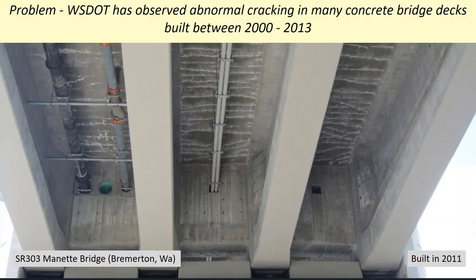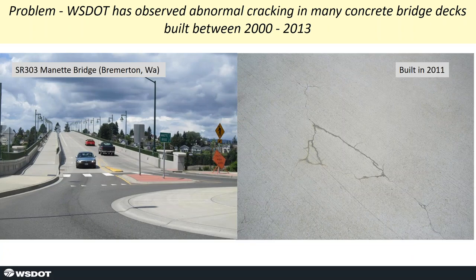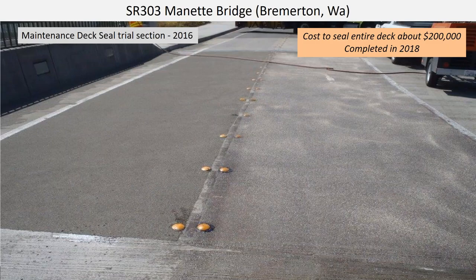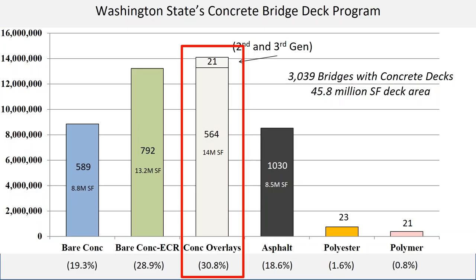And then on the bottom side, you can see for whatever reason, whatever combination of reasons, the deck had a lot of cracks in it from the very beginning. And we were recognizing this as a whole, and Anthony kind of already just talked to you about the changes we made in our deck concrete. So on this particular bridge, you can see here, has some pretty severe cracking in it. What we did is to seal up the cracks, maintenance went out and did a seal coat on the whole bridge, and we're hoping that that will do a better job at sealing up the cracks.